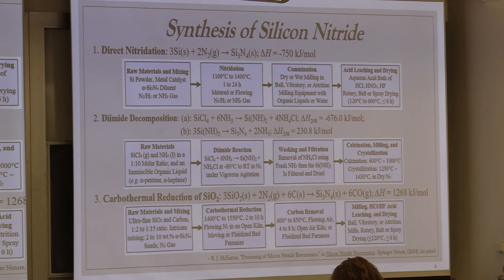And the third process is called carbothermal reduction of silica. You take silica, nitrogen and a carbon source and put them in a furnace together. This is an endothermic reaction, so it requires particular heat to get it to go. In fact, Raymond probably knows this story, but his father developed a very low-cost method here at the University of Utah where he took clay and coal and combined them in a nitrogen furnace to produce low-cost silicon nitride, and made quite a splash at the time. Unfortunately, carbothermal reduction has taken a back seat to the other two processes, although there is one company, Toshiba, that still claims to have capabilities to produce it. It seems like they only use it for their in-house needs.